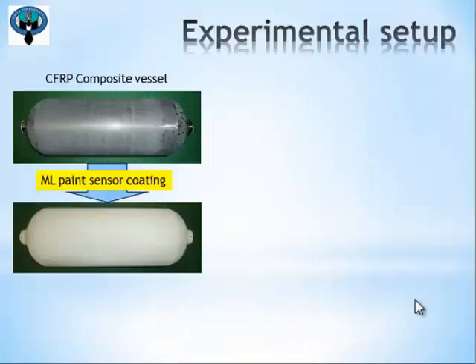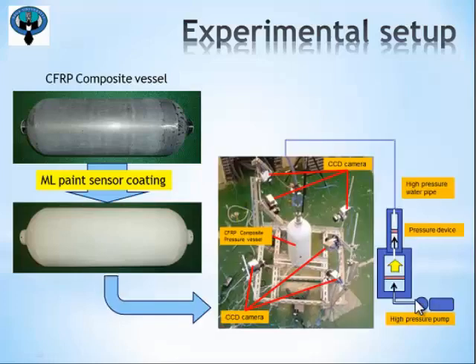Let me explain our experimental setup. This figure shows an examined CFRP composite vessel. ML sensor was coated on the whole surface of the vessel. The vessel was periodically pressurized by this high-pressure water pump. Light emission images from ML sensor were observed by 4 CCD cameras for side view and 2 CCD cameras for top view.